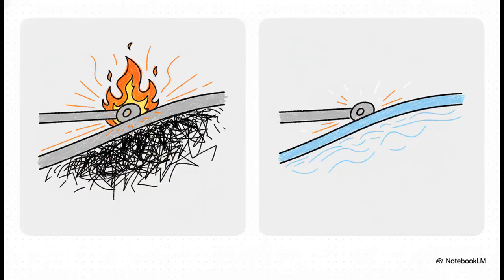And here, you can see exactly how a good coating fights back. In friction tests, a surface with no coating gets way, way hotter where it makes contact. But look at the coated surface. It actually lowers the temperature. And that is huge because less heat means less stress building up inside the material. The coating isn't just playing defense from the outside, it's actively managing the pressure from within.